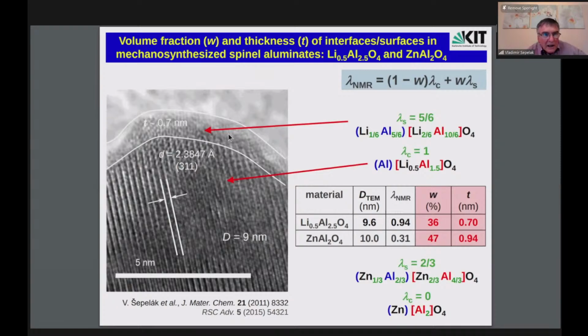Even if we look at the morphology of mechanosynthesized nanoparticles, in this case I show only zinc aluminate and lithium aluminate, from the experimentally determined degree of inversion using nuclear magnetic resonance spectroscopy, we can even calculate the volume fraction and thickness of this interfacial region. If we consider that the core of the mechanosynthesized material is like bulk material, and on the surface of these nanoparticles the cations are randomly distributed, that means we have a statistical distribution. In the case of 1,3 spinels, it is 5/6. In the case of 2,4 spinels, it is 2/3.